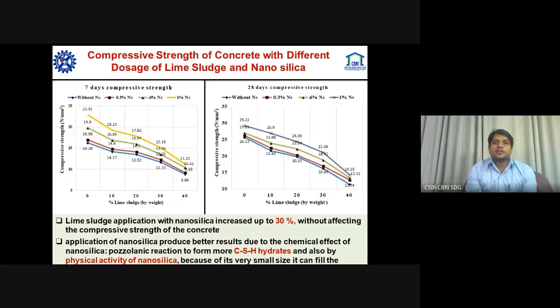So the compressive strength of concrete with different doses of lime sludge and nanosilica, it can be seen that lime sludge application with nanosilica increased the compressive strength. Sorry, lime sludge application with nanosilica can increase the lime sludge consumption up to 30% without affecting the compressive strength of the concrete. Application of nanosilica produces better results due to the chemical and also physical effect of nanosilica.